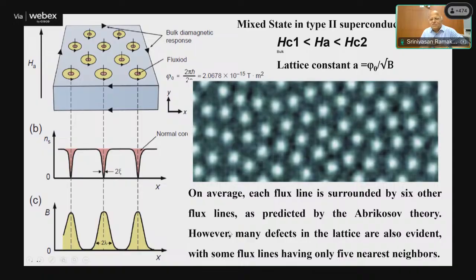It turns out that from free energy considerations, it has to form a triangular lattice, and the lattice constant is simply phi naught by root B. So when we increase the field, the separation, the lattice constant, becomes smaller and smaller. At the critical field, it just vanishes. So the mixed state of a type 2 superconductor is an unusual beast.